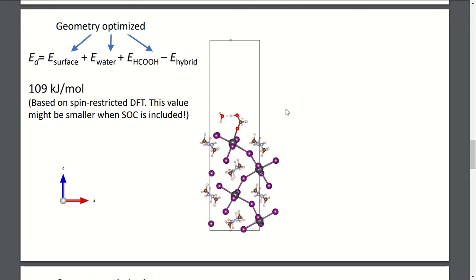So I guess, yeah, that is in the first paper, I think. In the supplemental, I think it's explained how to do it. Yes, so you can just get the binding energies in that fashion from the TPD. But nobody knows what the prefactor is, right? Depending on what prefactor you put in there, you can get any number. Right? No, pretty much. Unless you calculate the pre-exponential somehow for the desorption. Yes, there is a way to do it, right? There is a way. It will be questionable how precise.